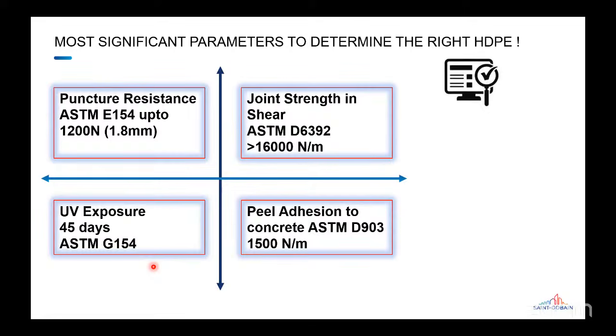Normally we apply the waterproofing membrane on the PCC or the blinding, and then the concreting is done after, in some cases, one month or three to four weeks. Till that time the waterproofing membrane should not lose its properties, and it should bond very well with the fresh concrete. So a UV exposure test is done as per ASTM G154. Then the joint strength, which is the strength of the overlaps of the membrane, is tested as per ASTM D6392. And then the peel adhesion, which is how well the membrane bonds with the concrete. These four important tests are carried out for any pre-applied waterproofing membrane to ensure that the quality of the product is as per the specification.